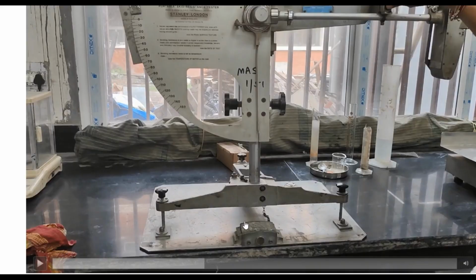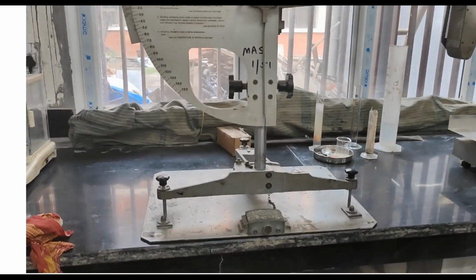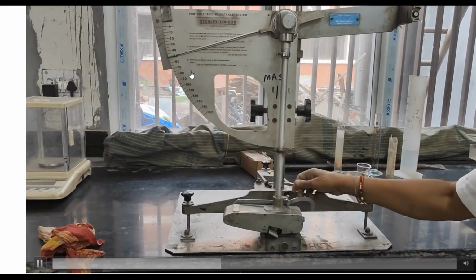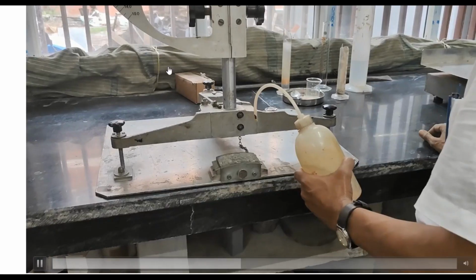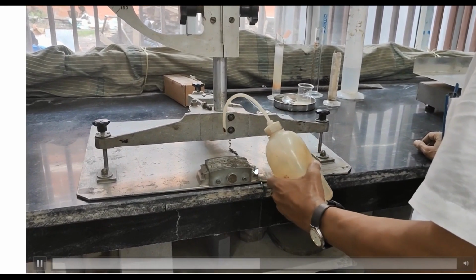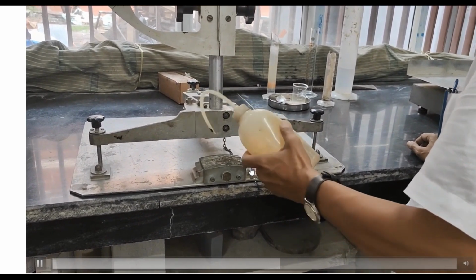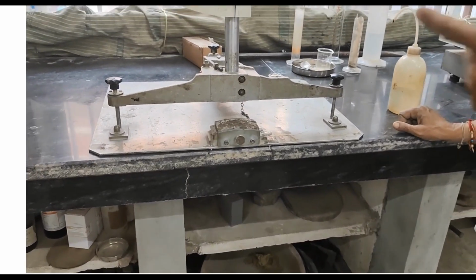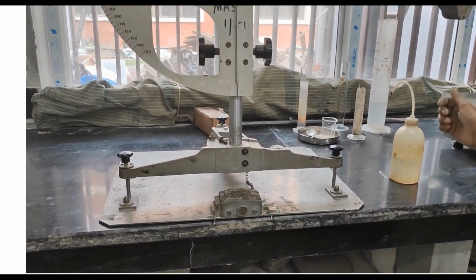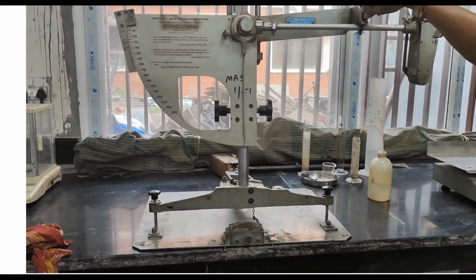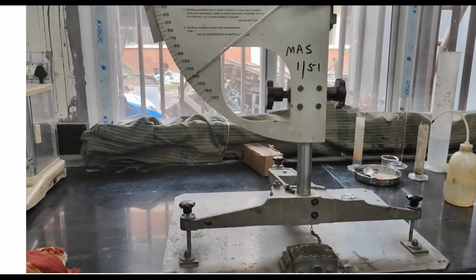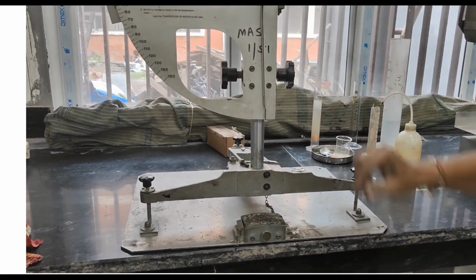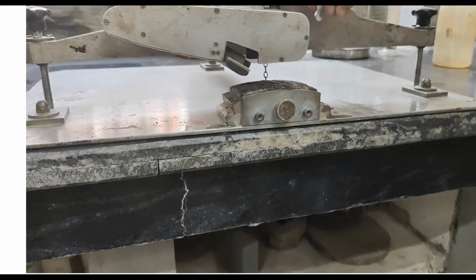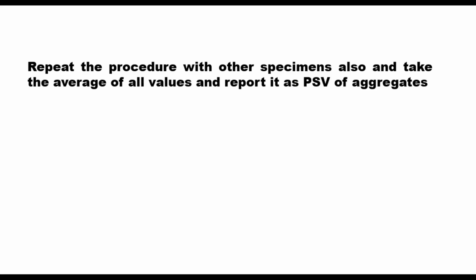Now you place the specimen here and bring this pendulum to the horizontal position, and then release this pendulum from the height, and you can read the PSV value here. This is 50. Now you sufficiently spray the water on the surface and also on the rubber slider, and then again carry out this test under wet condition. Repeat the procedure to get the friction value under wet condition, and now you can repeat this procedure with other specimens also to take the average of all values and report it as polished stone value of aggregates.